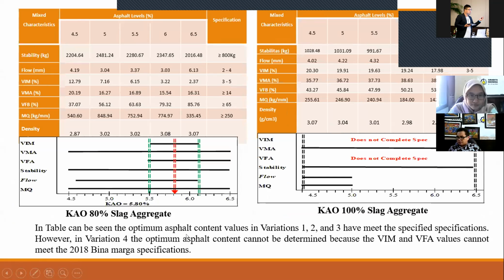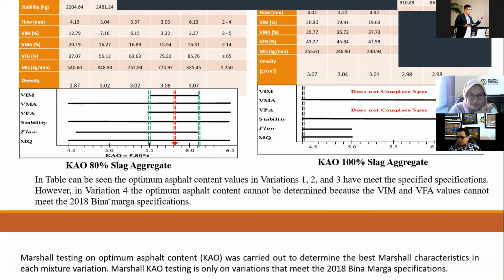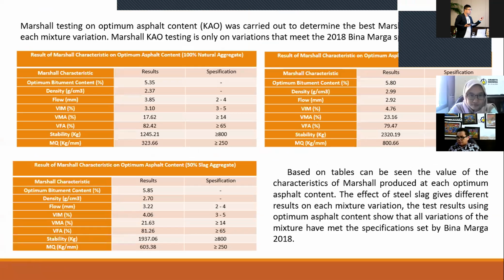In the table can be seen the optimum asphalt content values in variations 1, 2, and 3 have met the specification. However, for variation 4, the optimum asphalt content cannot be determined because the VFA and VIM values cannot meet the 2018 Bina Marga specification. Marshall testing at optimum asphalt content was carried out to determine the best Marshall characteristics in each mixture variation. Marshall KAO testing is only on variations that meet the 2018 Bina Marga specification.